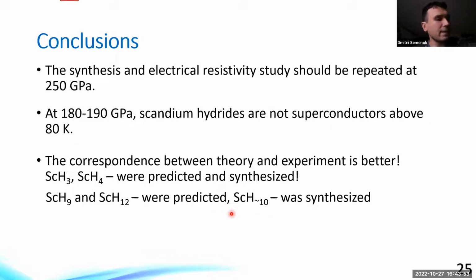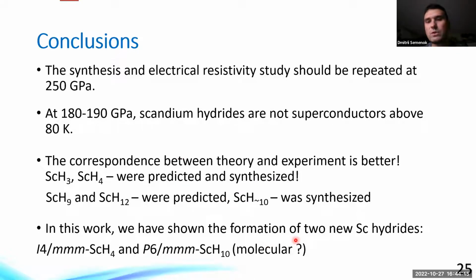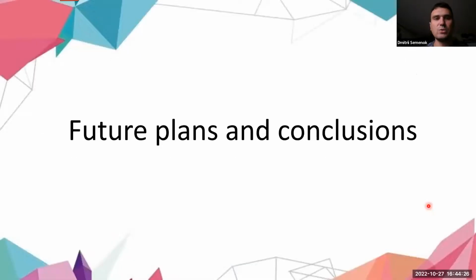And I think that an accuracy of plus or minus one hydrogen is still acceptable. So I think the prediction actually is quite accurate, and we can consider it a successful case of theoretical prediction of the formation of higher scandium hydrides. And yes, this prediction was confirmed in the experiment. We have shown the formation of two new scandium polyhydrides, again ScH4 and ScH10, with probably a molecular hydrogen sublattice and a hexagonal sublattice of scandium metal. Okay, that's almost all, a few last slides, and I will finish my presentation.